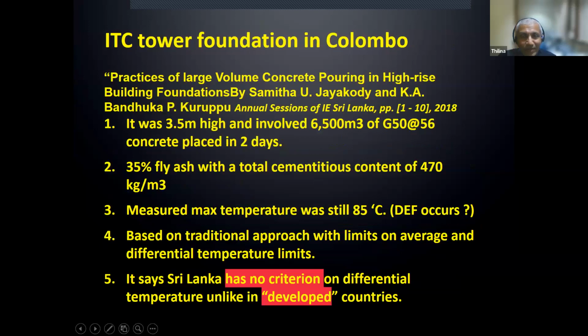Now, I just thought, once I announce it, Bhanuka sent me this paper. I think those from Sri Lanka should have a good look at that paper after this presentation. It's a very good attempt to get things in order, but there are a few things they probably missed. And it's about 3.5 meters high, involves 6,500 cubic meters of G50, grade 50 concrete at 56 days. And it has 35% fly ash with a total cementitious content, that is Portland cement plus fly ash, of about 470 kilograms per cubic meter. It's a very, very rich mix.